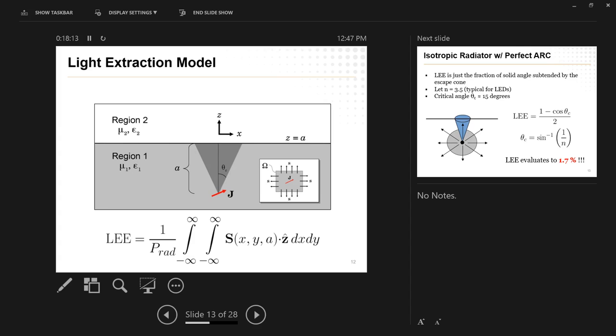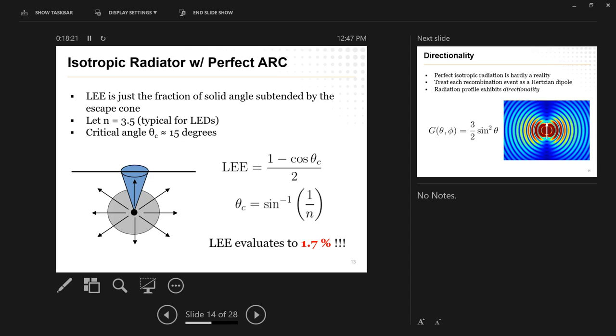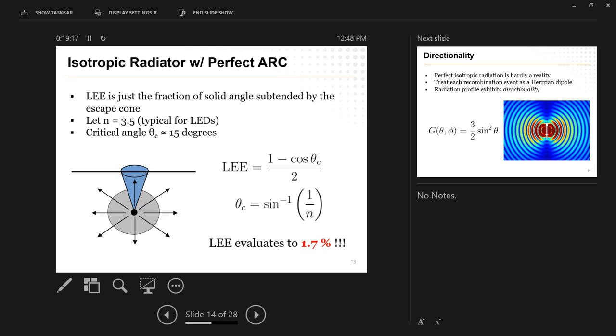So, fun fact, this is actually not very useful to do this in rectangular coordinates, so what we're going to do is re-express everything in spherical polar coordinates when we do these integrals in a moment. So, for example, let's say, for argument's sake, there's an isotropic radiator here, which doesn't really exist, but we can argue it anyway because it's simple. And so it's just spewing out energy equally in all directions, so that Poynting vector will just be constant as a function of radius. And so the total light extraction efficiency will just be the fraction of this solid angle relative to the entire sphere. So, basically, it's the solid angle of a cone divided by 4 pi steradians, which you get. So it's a pretty straightforward calculation. You get a nice closed-form solution, 1 minus cosine of the critical angle divided by 2 here. So that divide by 2, I believe, comes from the fact that there's nothing happening down here. So all the energy that goes down is lost forever, and the absolute most extraction efficiency you can get in this model is 50%. So that's where that factor of 2, I believe, is going to go.